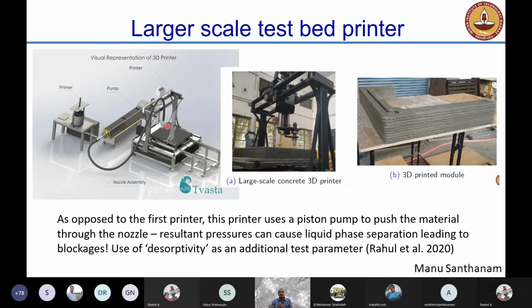Okay, so in one stroke, nearly 75 kilograms of the material could be pushed through the pipe, which carried it to the nozzle, and because of which our printing here was restricted to less than 75 kilos of material at a given time. Why is that? Because when the pump is going backwards, it is not pushing any material into the pipe. So you're basically going to be pushing air in the pipe, and that's a bad thing to do, right? You want the material to be continuously getting pushed into the pipe, just like your conventional concrete pumping operation, right?